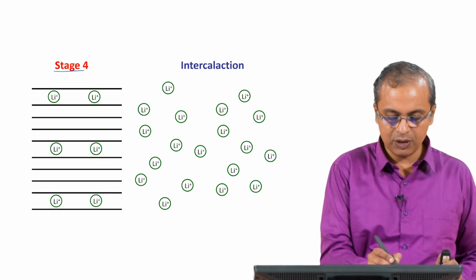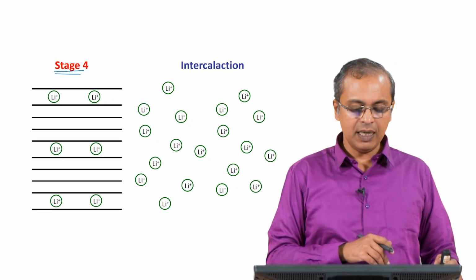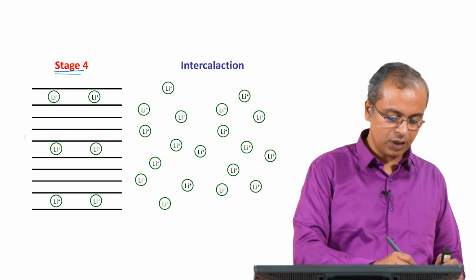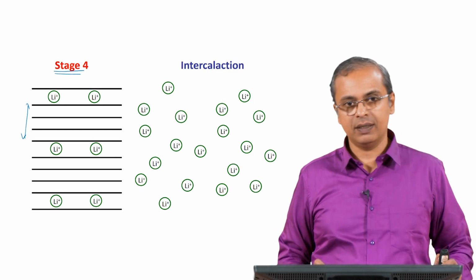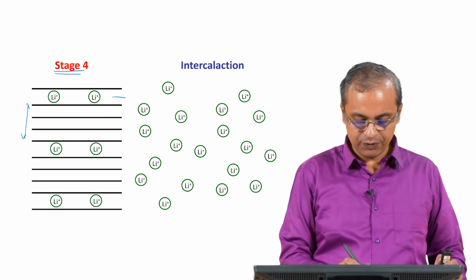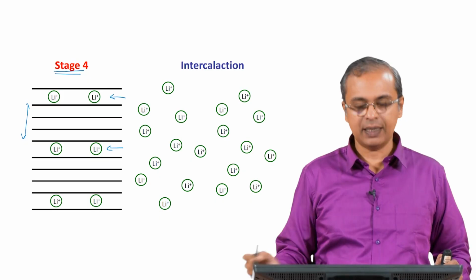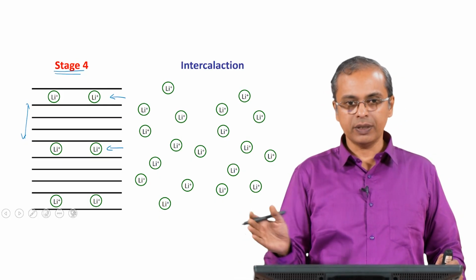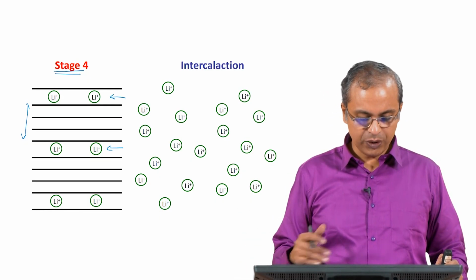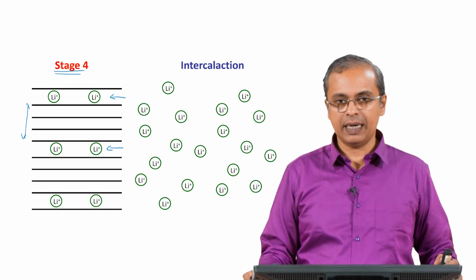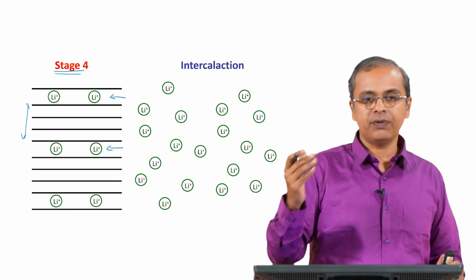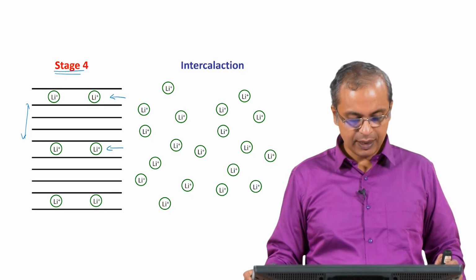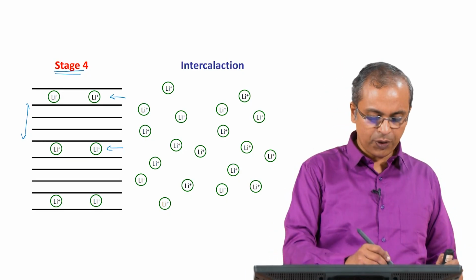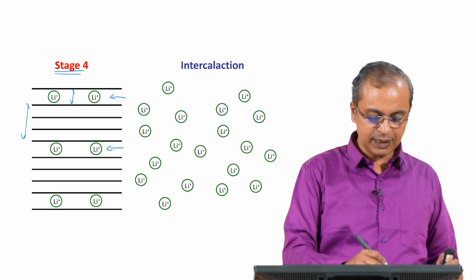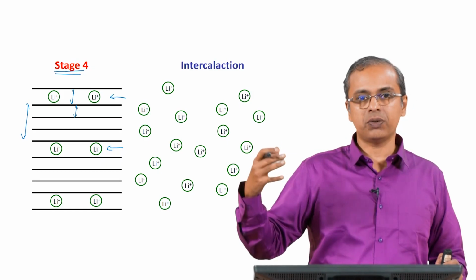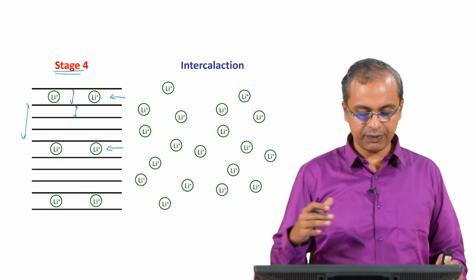Okay. So what happens, for example, when you do this, you will notice this is stage 4, this is called stage 4. So it is happening in reverse. Stage 4 simply refers to this idea that there are 4 layers of graphene between 2 adjacent layers of lithium ions that have intercalated into the system. So between 2 adjacent layers of lithium ions, you have 4 layers of graphene. Okay. And what I will also point out is that you see here the spacing has gone up, this spacing is a little larger than this spacing, that is because the ions have come in there. Okay. So the ions have come in there.